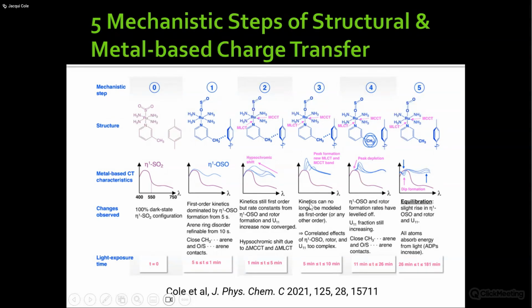So we can't accept that that's really first order anymore, and correlated effects are definitely taking apart. They're probably at the moment, for us at least, too complex to model, but we can certainly observe them and get their mechanism by using the experimental data. And you saw C6, this is the methyl group, and at this point it's wobbling like crazy. That seems to be associated with this change in the optical absorption here, and then it equilibrates and calms down, if you will.